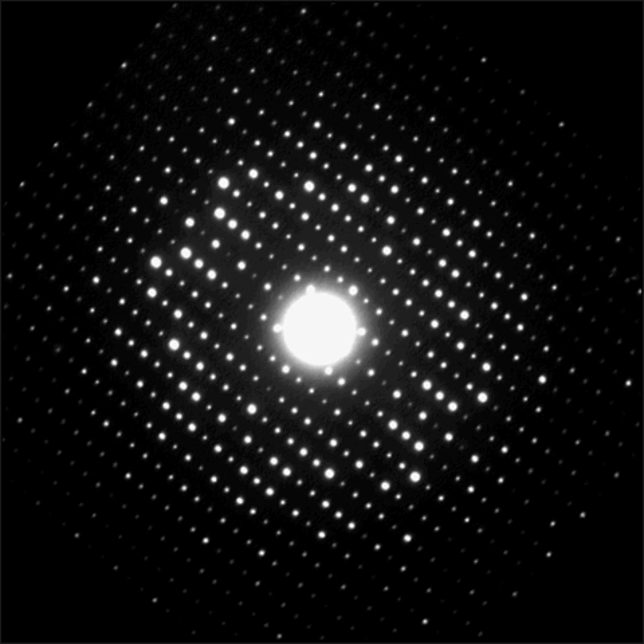This is of crucial importance since in the thicker parts of the crystal the exit wave function, which carries the information about the intensity and position of the projected atom columns, is no longer linearly related to the projected crystal structure. Moreover, not only do the HREM images change their appearance with increasing crystal thickness, they are also very sensitive to the chosen setting of the defocus delta F of the objective lens. See the HREM images of GaN for example.